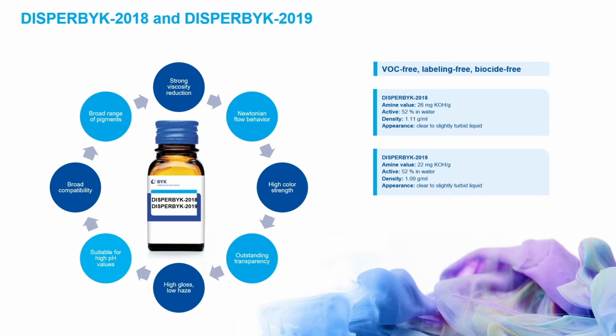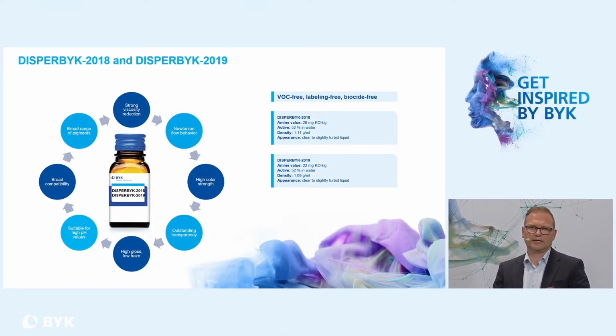When you use it in pigment concentrates, you will achieve a strong viscosity reduction. For you, it means you can achieve high pigment loadings with a Newtonian flow behavior. When you add these pigment concentrates then to your base paint, you achieve highest color strengths with organic pigments and transparent iron oxides, excellent transparency combined with high gloss and low haze values. The Disperbyk 2018 you can even use at very high pH values, thinking about silicate paints or water-based epoxies. And it shows really a broad compatibility over a large number of binder systems. And as mentioned, you can use it really for a broad range of pigments, not just reduced to inorganic or organic pigments, even transparent iron oxides or carbon blacks.